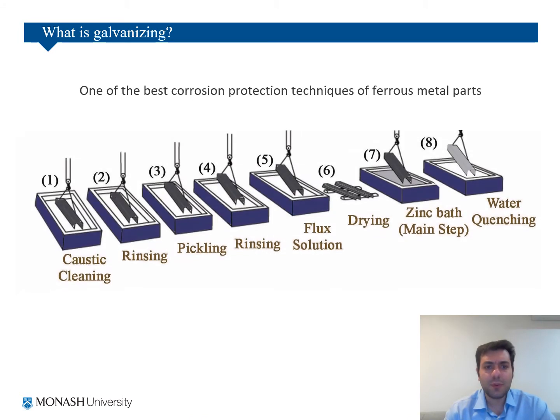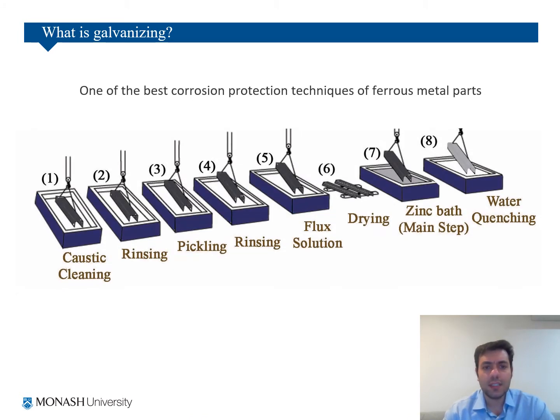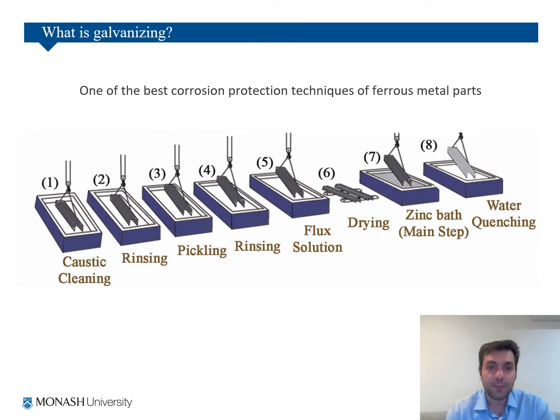So these are the steps for galvanizing: caustic cleaning, rinsing, pickling, rinsing, flux solution, drying, zinc bath, which is the most important one, and water quenching. So in step 7, metal parts are exposed to a high, or let's say elevated temperature.